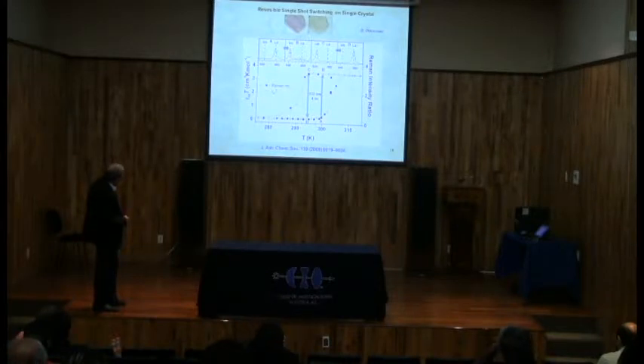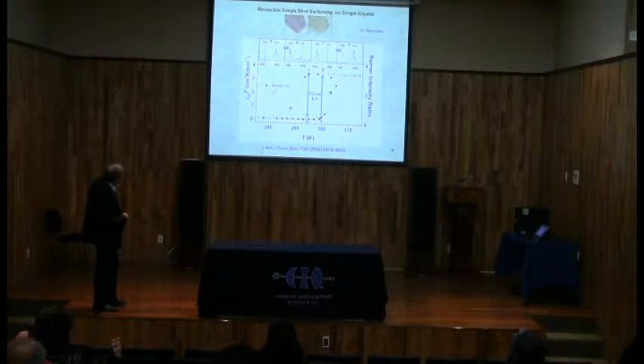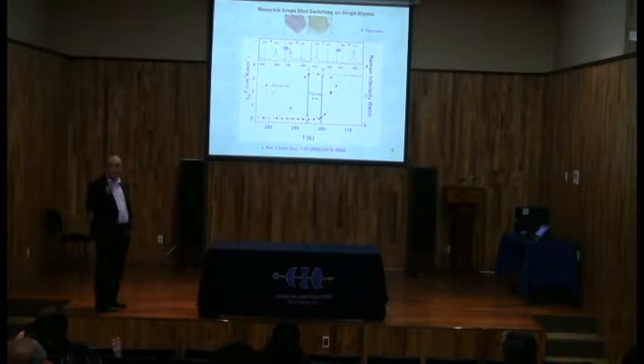If you prepare your system here at point A, where you are in the low spin form, and then you look at the Raman spectroscopy, you see that the spectrum is pure low spin state. You have nothing in the high spin form. The system is 100% in the low spin state. If you send your pulse, you see by Raman spectroscopy that you go from this spectrum to this one, which means that you have no low spin state and you have generated the high spin form. That means that you are going from point A to point B by sending your first pulse.